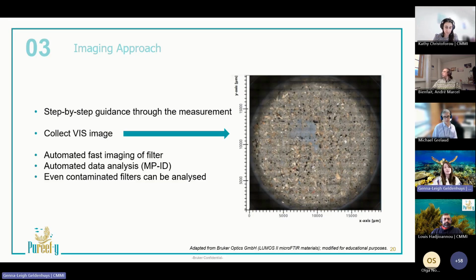It's important to note that you won't miss any particles. Even transparent or overlapping particles or agglomerated particles are detected, as it's not based on visual contrast, but rather on spatially resolved chemical resolution. The Lumos 2 does not replace good sample preparation, but I have to say it's far more forgiving of samples with complex matrices or samples that are highly contaminated, because it identifies microplastics based on chemical information. So even filters like in the image below can very, very effectively and efficiently be analyzed.